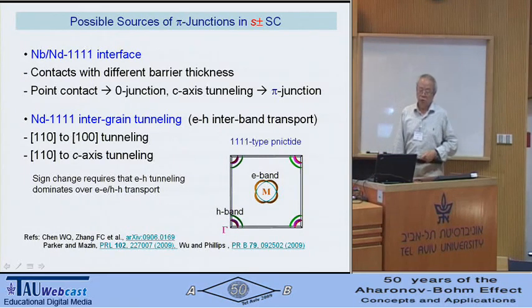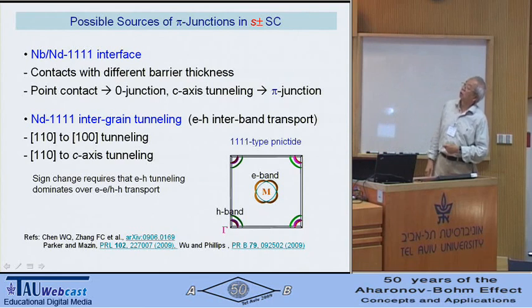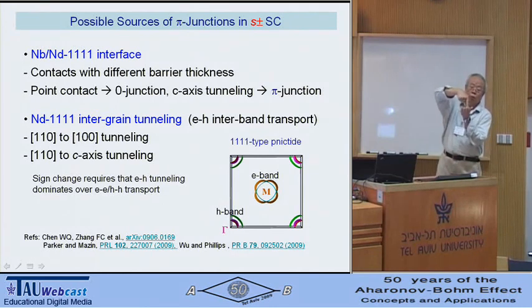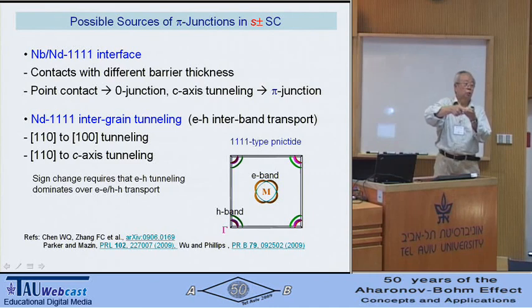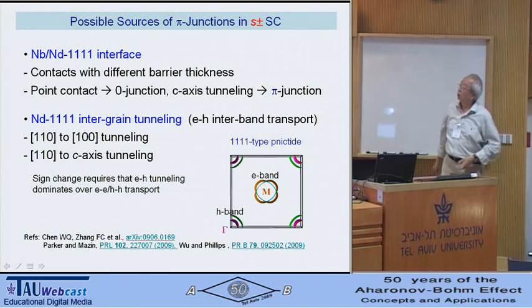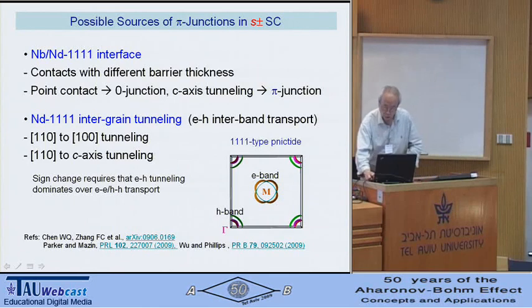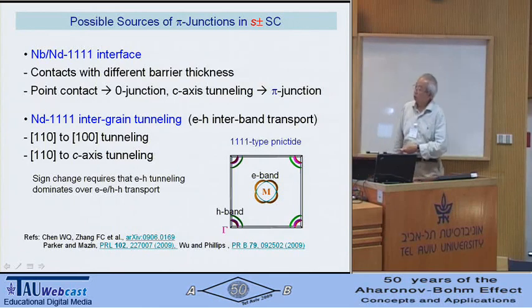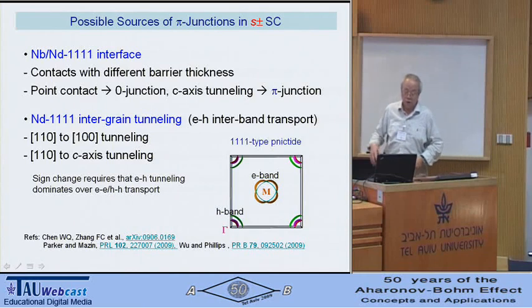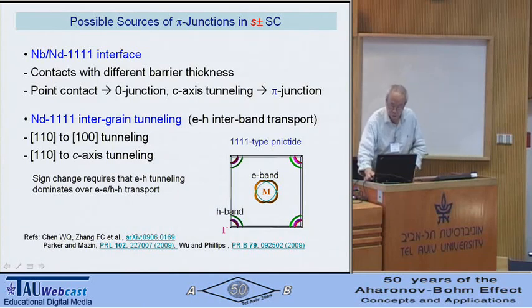Then if you are interested, you can find out what the possible sources of a pi junction are in this experimental setup. We say there are two possibilities. One is at the niobium iron pnictide interface. In other words, the point contact right at the contact. The other is in between the contacts, where there is polycrystalline material. You could have a sign change over there. So those are the two possibilities. And in the literature already, there are some papers that discuss such possibilities.